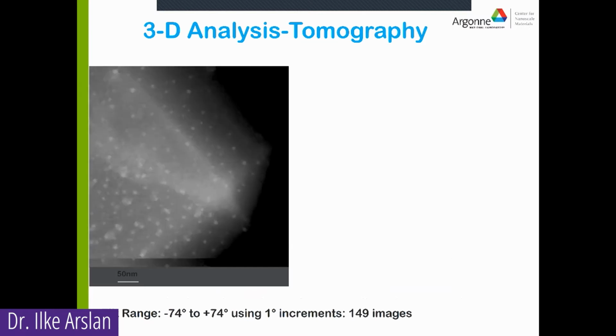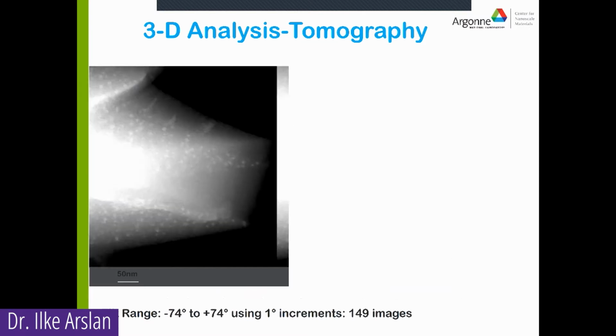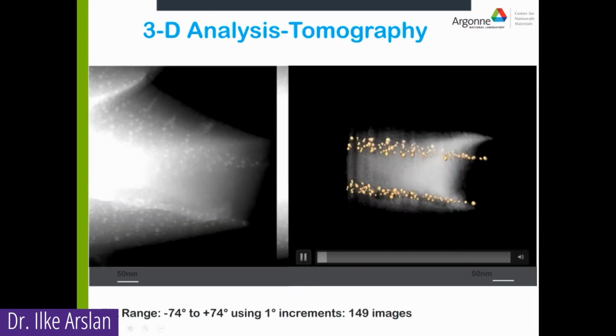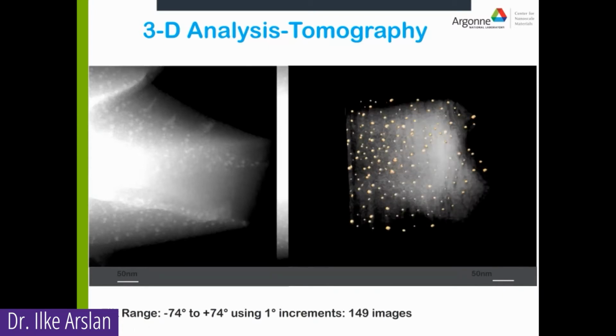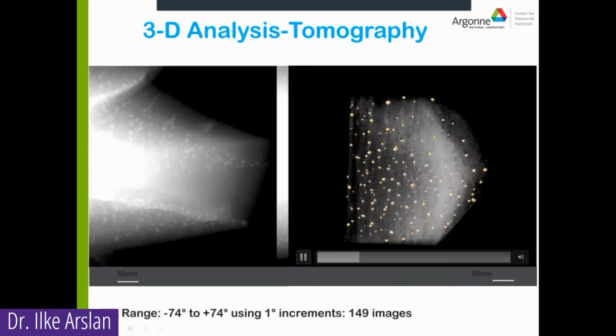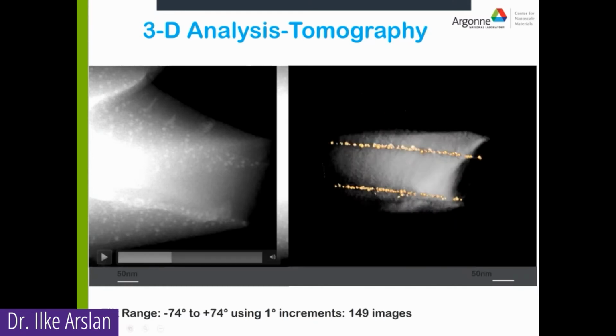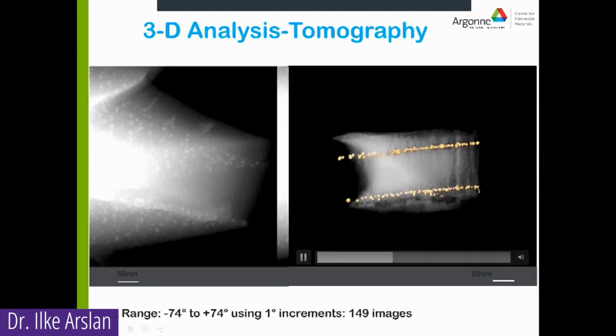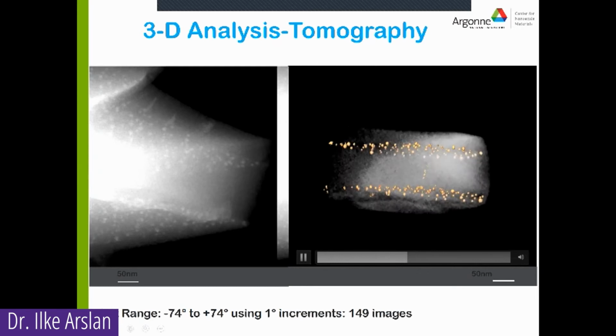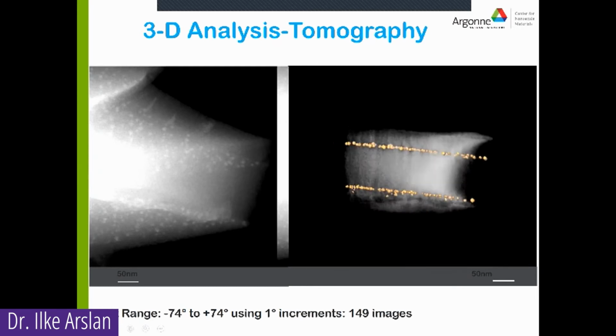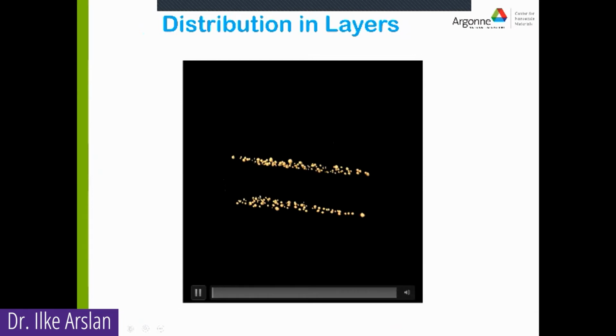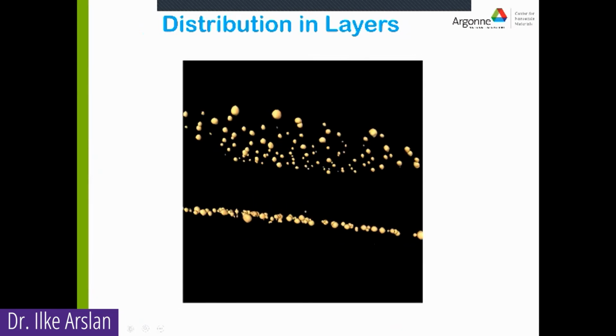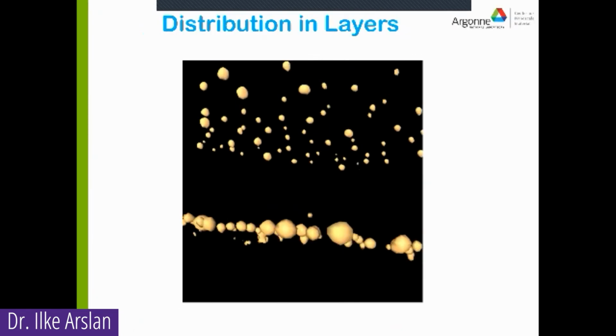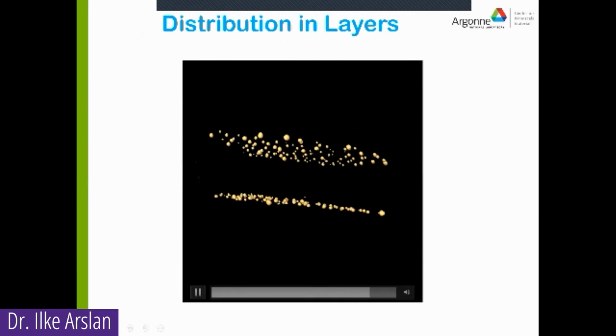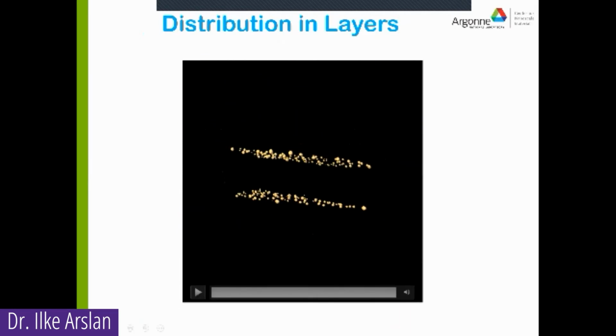that my camera's off. And we were able to get, okay, perfect. So we were able to get a 3-dimensional reconstruction, and you can see that the quantum dots are all in these 2 layers. And the white is the silicon. And if we take away the silicon and just look at the tin quantum dots and we zoom up, I call this my Star Wars movie, you can see that there's this one little quantum dot that has formed outside of the layer. So we caught one of those that we had seen in cross-section in 2 dimensions.